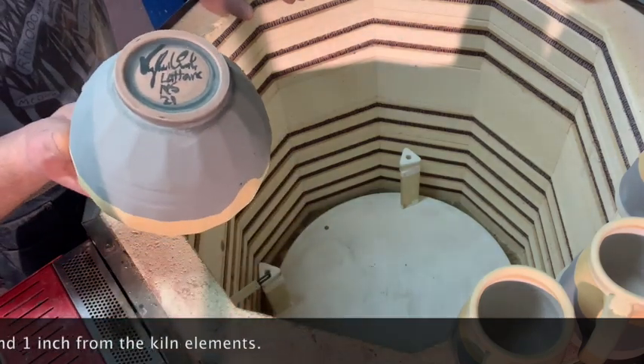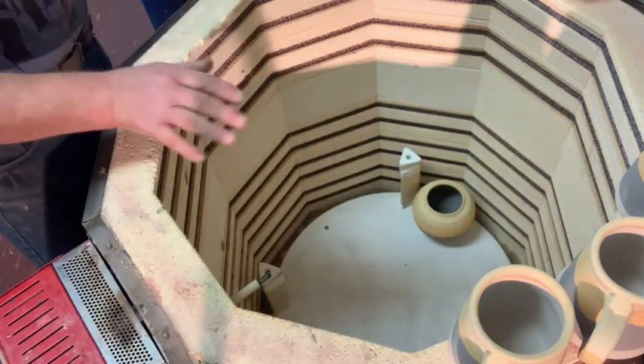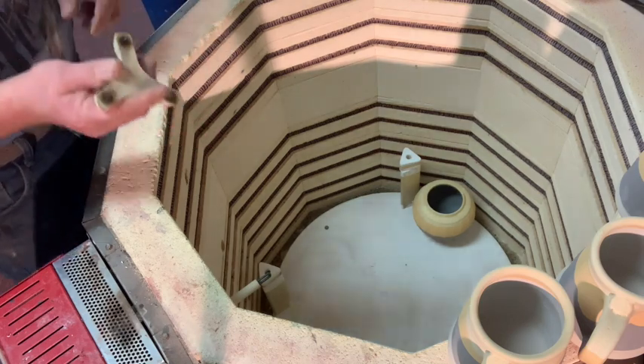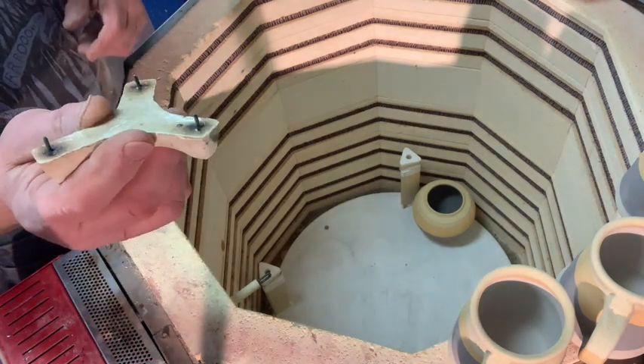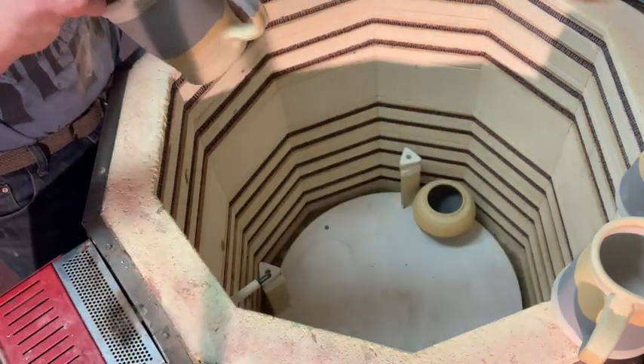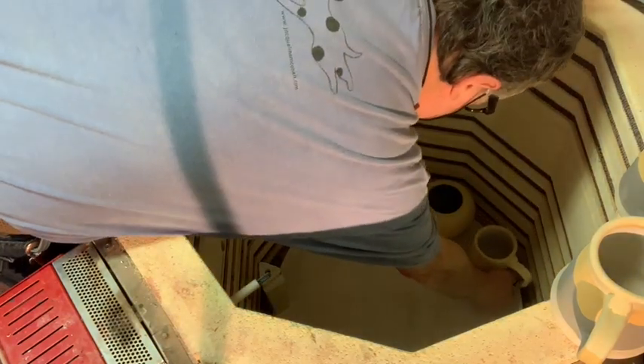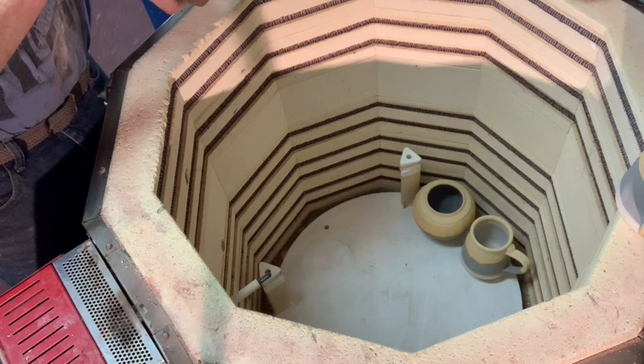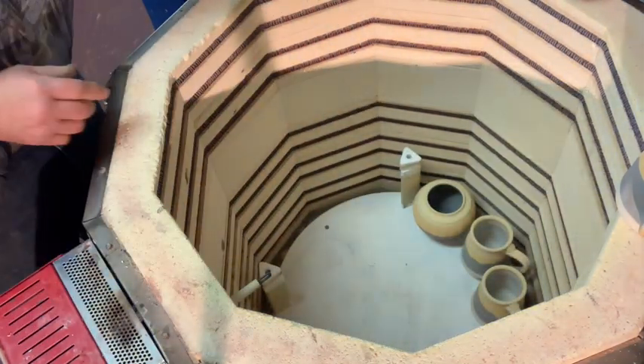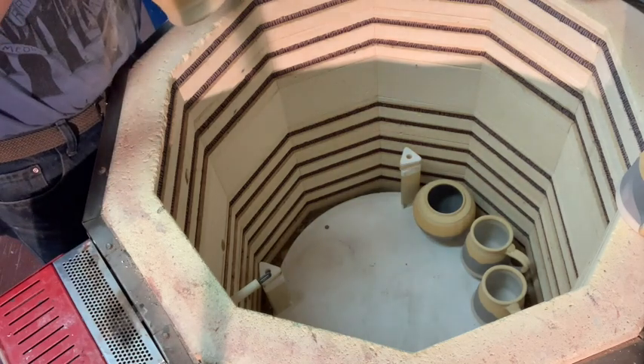That one's wiped - I signed the bottom with an underglaze that I used to sign with a paintbrush. Place it down and try to get everything approximately within that height. I use stilts to fire my kilns - if you're a beginner or someone new to the channel, this is what I fire my pots on - little stilts with pins. So I don't wipe the bottom of these; they're glazed on the bottom. I've found that customers over the years like the smoothness of a finished glazed bottom. The goal is to get as many pieces in that shelf as you can, making sure you don't get anything closer than about an inch from the elements.